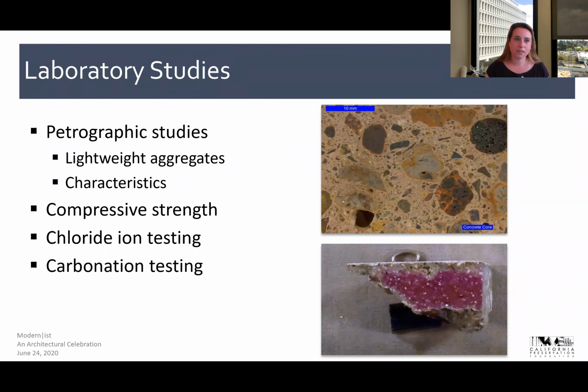We did do laboratory studies. We did both petrographic studies as well as physical. We had some cores that had been taken out for some mechanical work, so we had some good cores that we could test and get compressive strength values on. And both the physical testing and the petrographic testing basically aligned with what we expected based on the mix design. The compressive strength is as had been specified. We had the same materials, the lightweight aggregate, and really the same characteristics that we saw within the mix design. We also did some carbonation testing, looking at how that might be influencing the rate of corrosion, as well as looking at chlorides and the amount of chlorides that we had. And we did find chlorides, especially on the west-facing elevations. The air-carried chlorides off of the ocean were within the concrete.